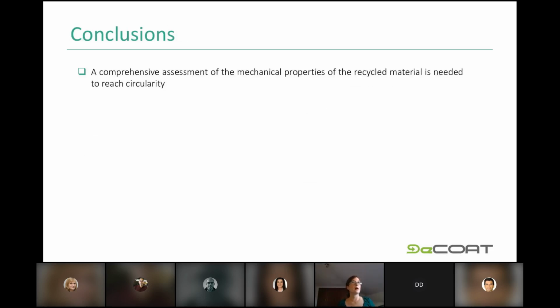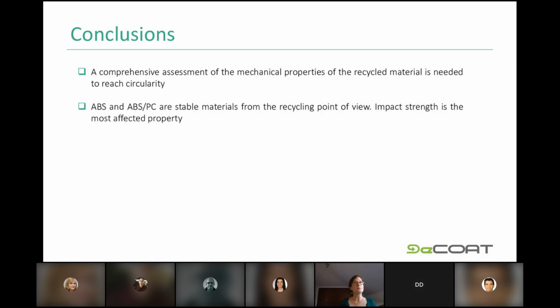So in conclusion, we have performed a comprehensive assessment of the mechanical properties of all the recycled materials, and it's something that is crucial in order to reach the circularity. If you want to choose the best application for the recycled material, you need to have a clear overview of the mechanical performances of those materials, of course. Also, we can conclude that ABS and ABS-PC are stable materials, generally speaking, much more stable than we have expected at the beginning of the project, in fact. Although the impact strength is the most affected property, and so it can affect the selection of the final use for these recycled materials.